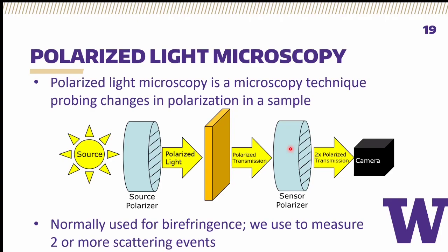If in the cross-polarized case, as we call it, there is an image that appears, that means there's an interaction of the polarization vector of your incident light with your sample. This happens most frequently in the literature because of a birefringence effect, when you have a largely anisotropic material, anisotropic meaning different directions, not uniform in 3 different directions. So you have this anisotropic material that has different indices of refraction along the symmetric and asymmetric axes that cause your light to bend 90 degrees in polarization space in your sample, causing you to see an image in the cross-polarized case. And this can happen either due to crystal structure anisotropy or because you have a nanowire structure, and that can cause a birefringence effect even in symmetric crystals.